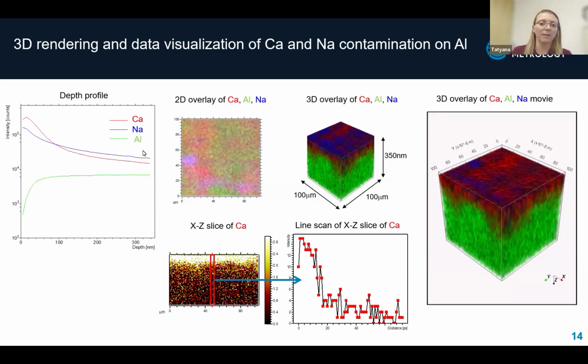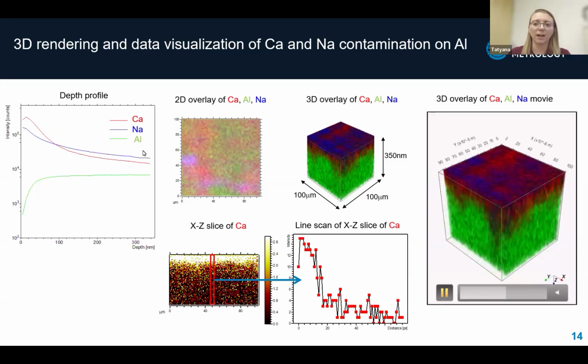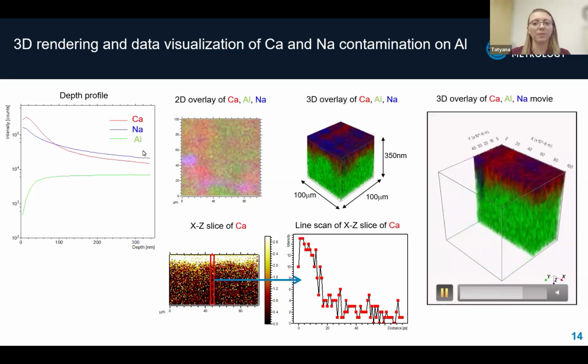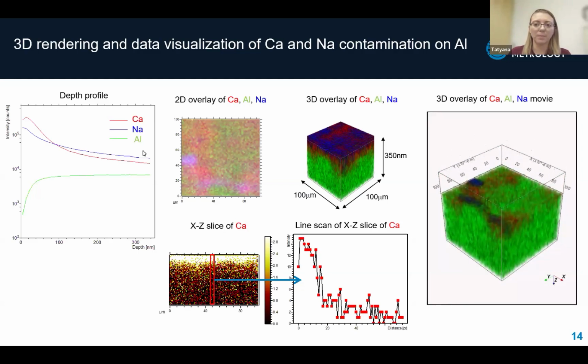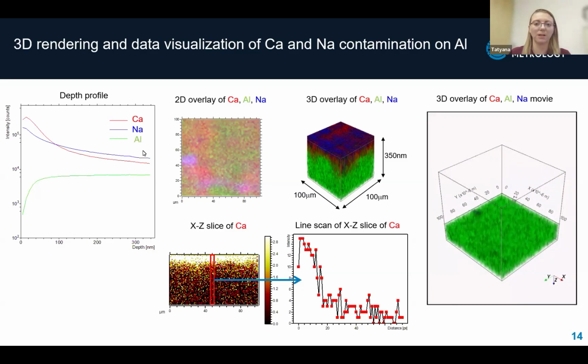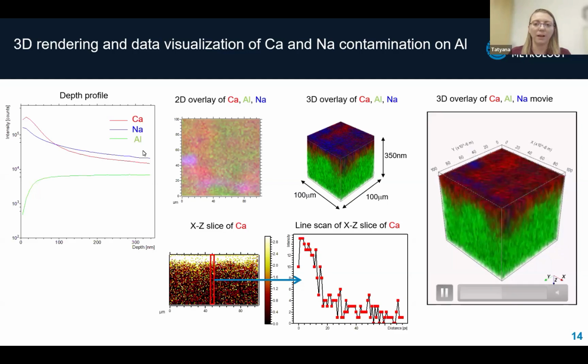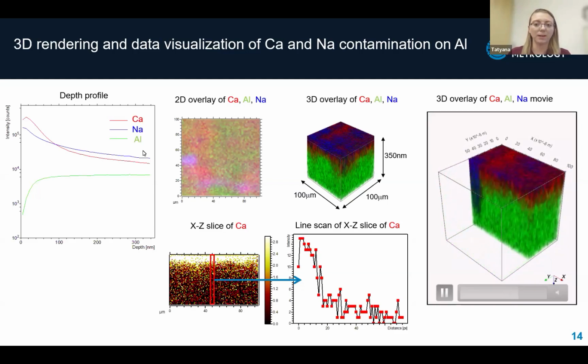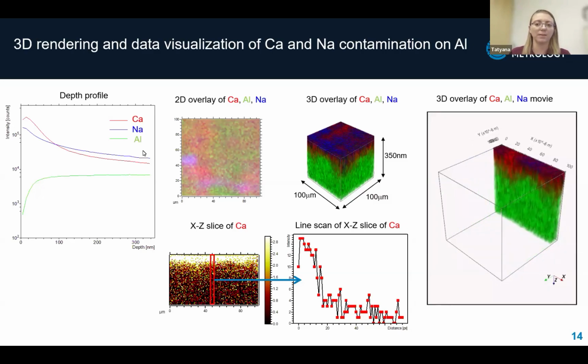If we measure this sample with EDS, we would see something like similar results. Next, the XZ slice of the depth profile of calcium gives us a side view of how the calcium is distributed vertically, while the line scan gives relative numbers to the colors in the image. The 3D reconstruction takes our analysis further, creating a 350 nanometer deep volumetric visualization. The color coding is the same as before. This three-dimensional mapping allows us to understand how the surface contamination penetrates into the sample. ToF-SIMS provides both visual and quantitative data, allowing for detailed multidimensional analysis of contamination.